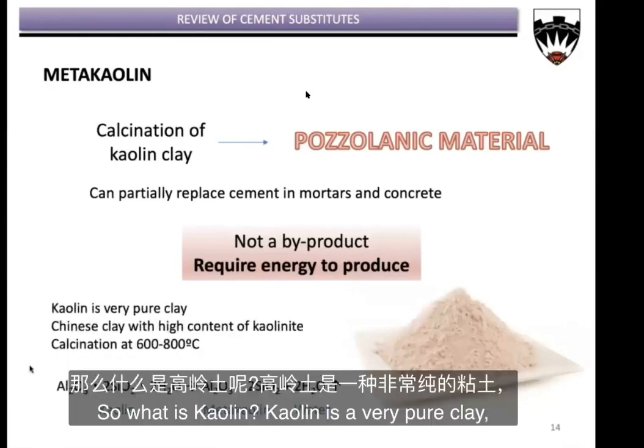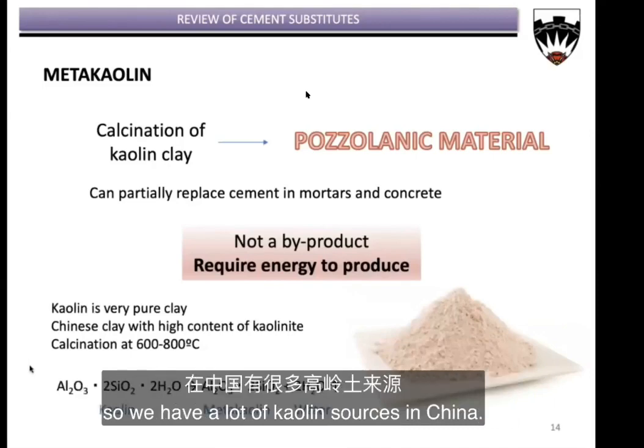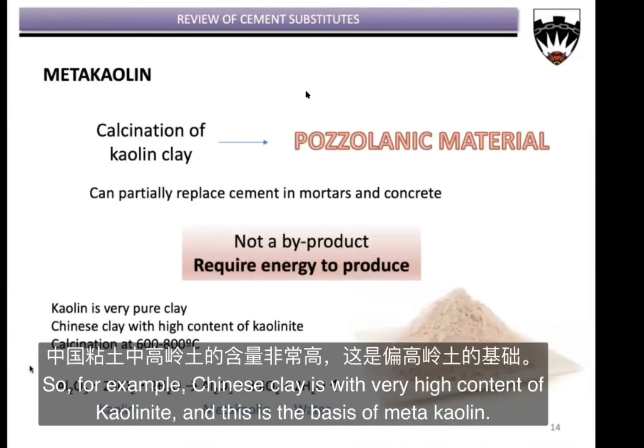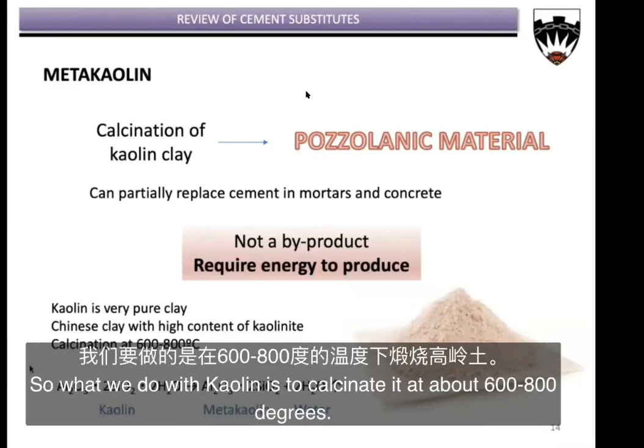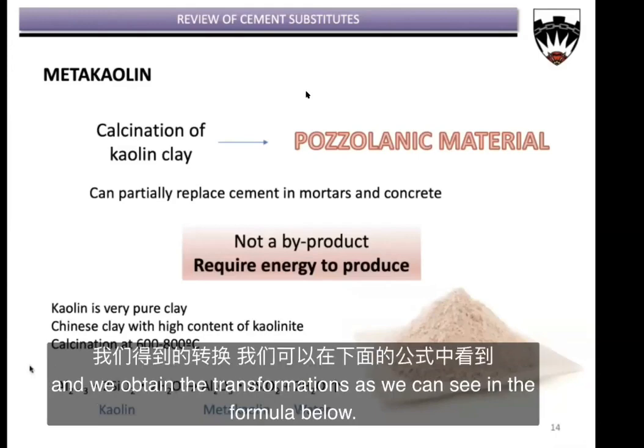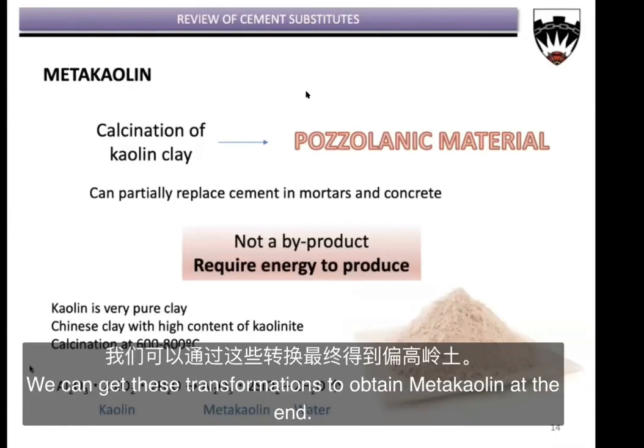So what is kaolin? Kaolin is a very pure clay. We have a lot of kaolin sources in China. So for example, Chinese clay has a very high content of kaolinite. And this is the basis of metakaolin, right? So what we do with kaolin is to calcine it at about 600 to 800 degrees. And we obtain the transformations, as we can see in the formula below. We can get these transformations to obtain metakaolin.